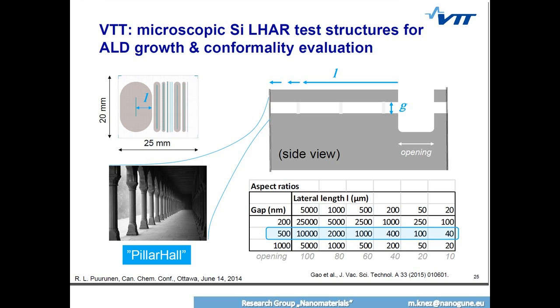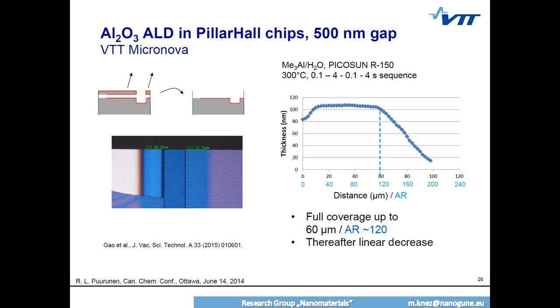Here, for example, these slides I got from Riikka Puurunen. They did those experiments with aluminum oxide, for example, with a 500 nanometer gap. So if you remove the roof, you can see below the roof there was a very nice deposition up to this point. And here you have a gradient. That means here you had exposure time which was good enough to get that far, but you could not get further. If you want to coat it further, you need to give it more time to diffuse in.